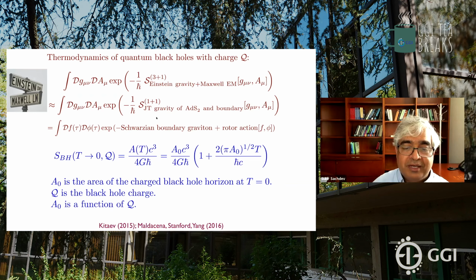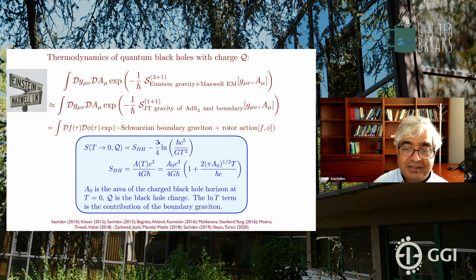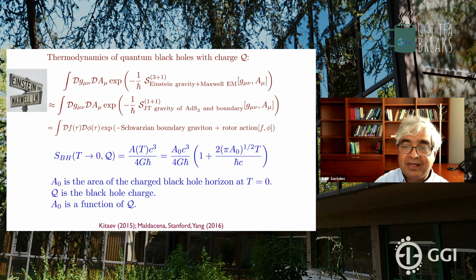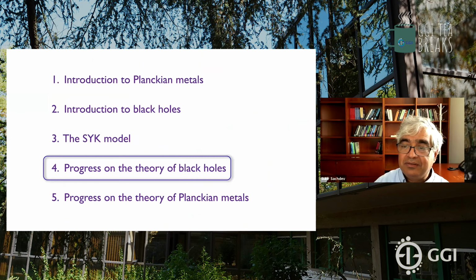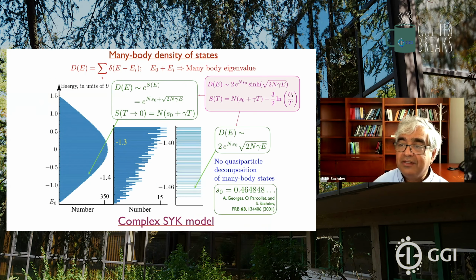Okay, so what do you get from there? Well, this is the correction. This -3/2 log T is the correction to the leading term, the Bekenstein-Hawking term. And in fact, that is exactly the correction here. The only thing different between them is this cutoff scale here, which is some U, the strength of the interactions here, and in the black hole case is determined by the mass of the black hole.